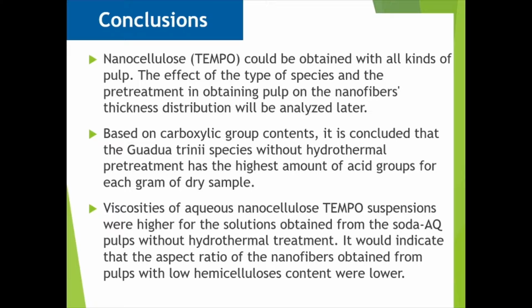The effect of the type of species and pretreatment in obtaining pulp, and of the thickness distribution of the nanofibers, will be analyzed later. Based on the carboxylic group contents, it is concluded that the Guadua trinii species without hydrothermal pretreatment has the highest amount of acid groups for each gram of dry sample.